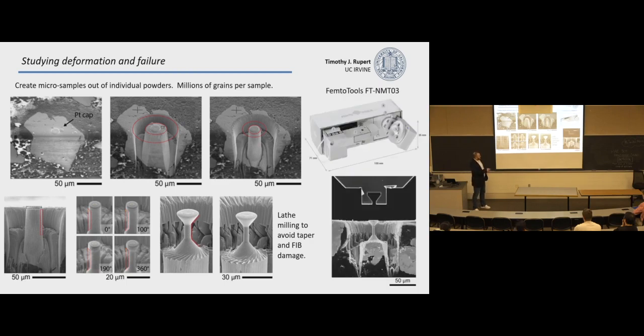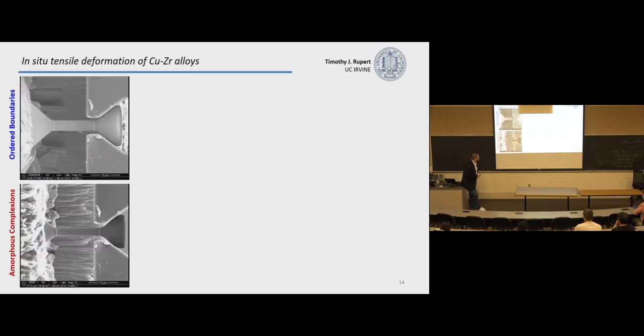We test these with this Femto Tools system. It's basically a little micro manipulator that goes inside of the SEM. What's nice is we can machine the silicon tip into whatever shape we want. In this case, we come down, go in front of that thing, hook it, and pull it up and deform it. So I'm going to show you some movies real quickly. On the top is the copper zirconium sample with ordered grain boundaries, and on the bottom is the one with amorphous complexions. Again, everything else is the same.